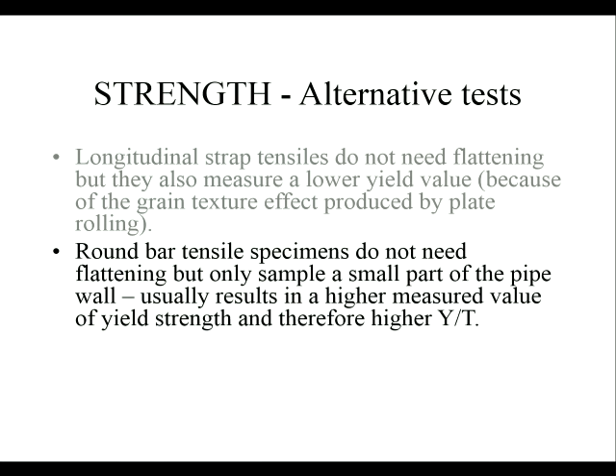Sometimes you can cut from the pipe wall a round bar test piece, a much smaller test piece from inside the wall. You have to do a lot of machining to do it. And this usually results in a higher value of the yield strength when you do that, because it's not got all the surface defects from the pipe which are contributing to the behaviour you measure. But sometimes, for some designs, it's the only way you can get a decent sample that is reliable when you do the test. If you've got a heavily deformed pipe surface, every measurement you take will give you a big scatter in results, and so you try to then pick more reliable tests just to check the basic material rather than to check the material and its manufacturing process, which is what we're doing with the API strap test.